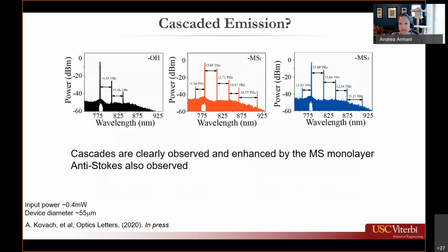So now, the next step is, is there cascaded emission? If we're getting significantly higher efficiency in the first peak, can that generate cascaded emission? And the answer is yes. So we clearly get cascades in the methyl group, at both polarizations. So this is comparing the silica group, so just the normal silica surface, with both methyl polarizations. Additionally, we get anti-Stokes generation. And we're never able to get anti-Stokes generation in just a silica device at the input powers that we studied.